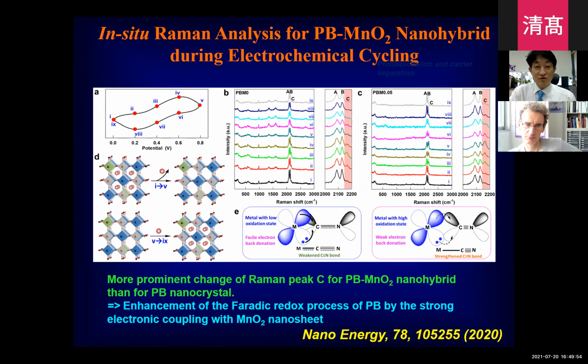Also, we did in situ Raman analysis. As you can see here, compared with the pristine Prussian blue, in the case of the manganese oxide hybrid we observe much stronger formation of the high energy peaks, which is related to the change of the cyanide ligand and to the oxidation of the metal ions. So it's the evidence for the enhancement of the electrode activity of Prussian blue upon the hybridization with the manganese oxide nanosheet.